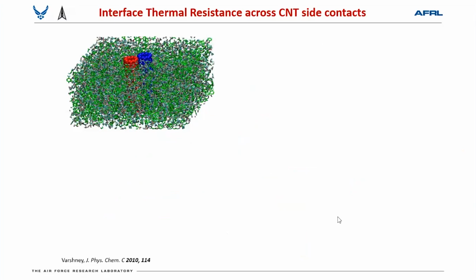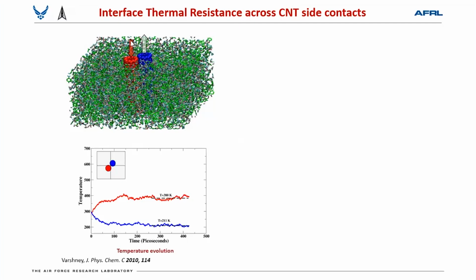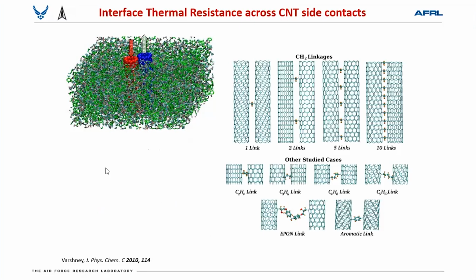Now I'm going to go to the thermal part. So what I said, thermally mixing carbon nanotubes to each other doesn't give you the improvement in thermal conductivity. So we want to look at this problem very carefully. As I said before, this is also a thermal interface design issue. So this is the case. We are putting two nanotubes next to each other, and we are heating one and taking heat out. And after equilibrating the situation, we see there's a disparity in temperature, even at the walls next to each other of this cold and hot nanotube. That means there's a significant thermal resistance at the interface of these two junctions.